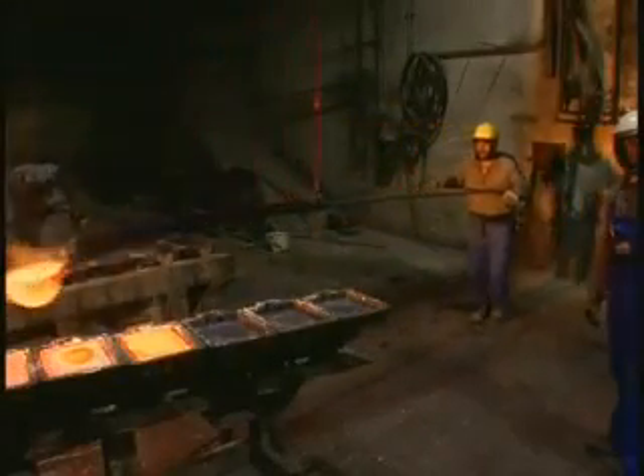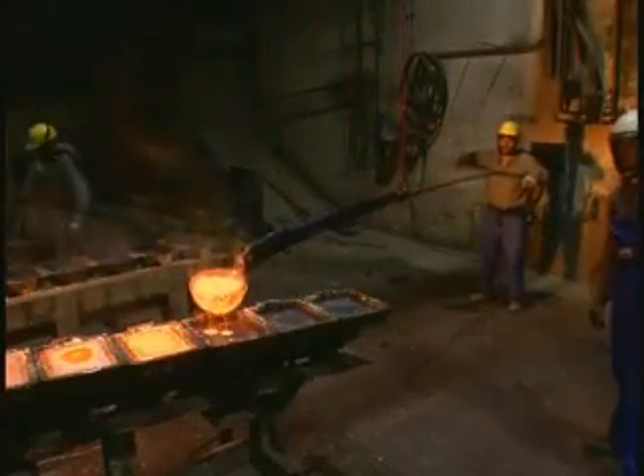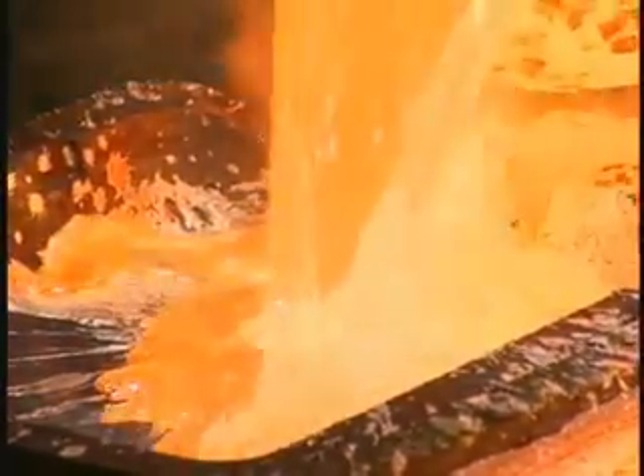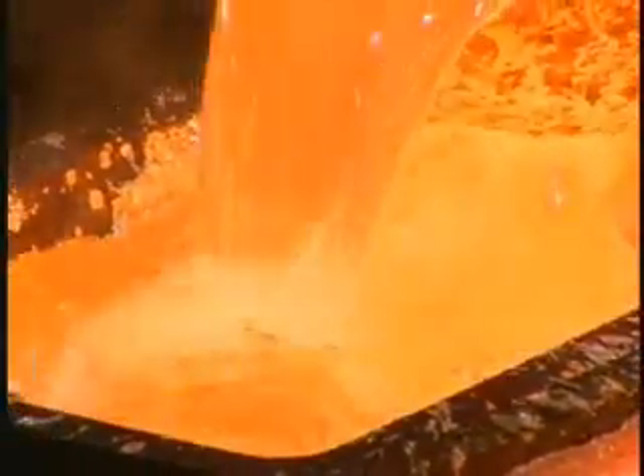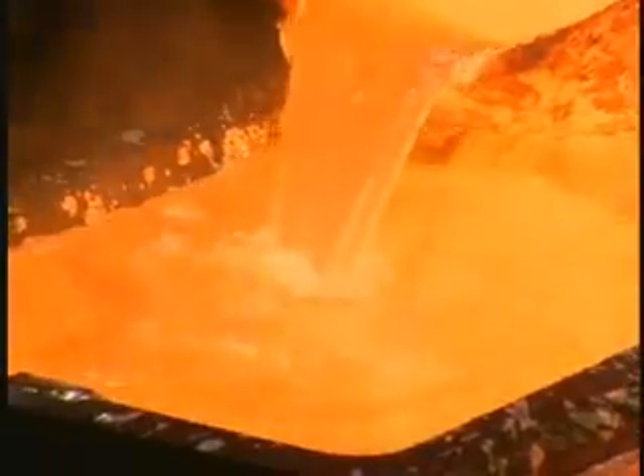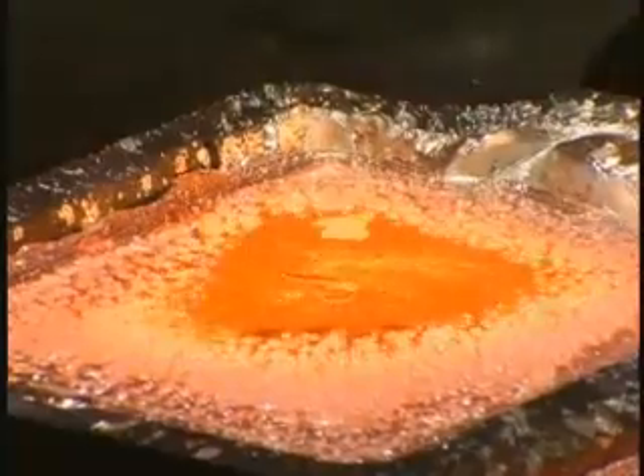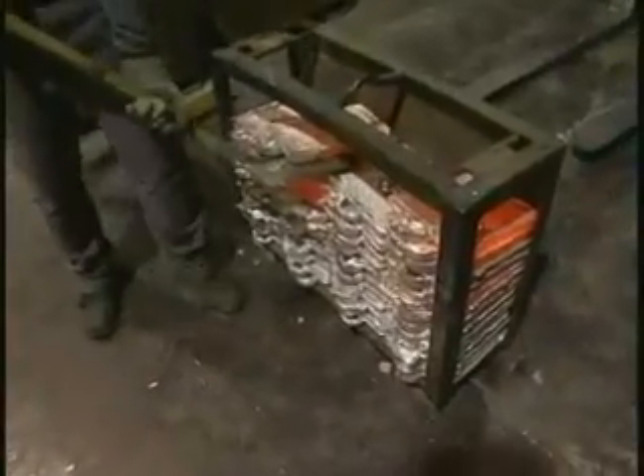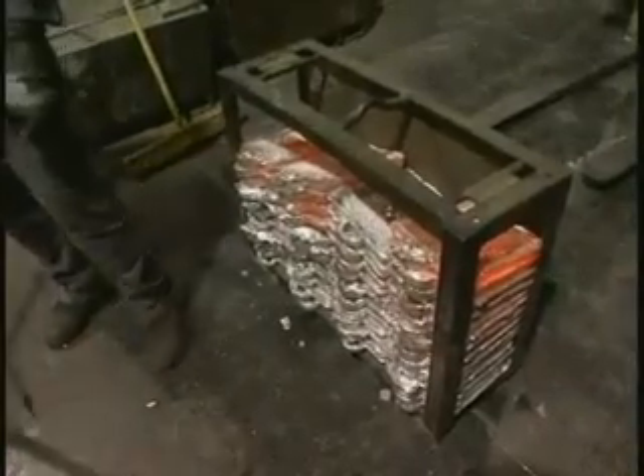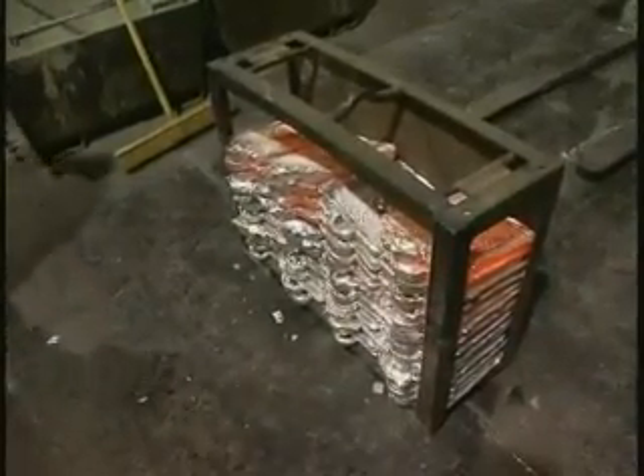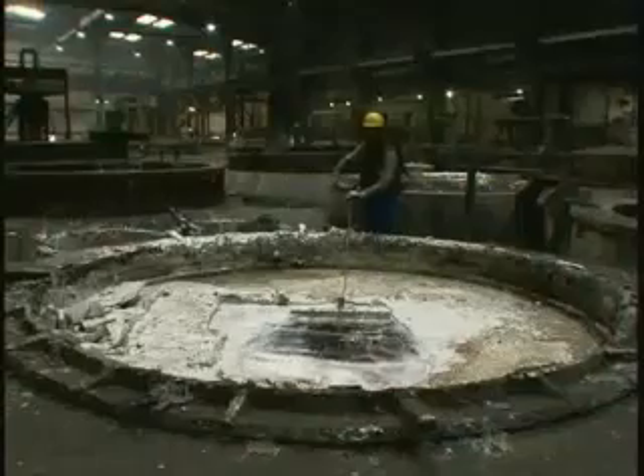In the lead smelter, every year up to 300 tons of silver are produced, for example. In a special cupellation furnace, the silver is freed from the residual lead and cast into handy 14-kilo bars. This is auriferous silver, which contains about 1 per mil gold and 0.1 per mil platinum metals. The dross is reprocessed. The byproducts thus obtained are utilized. This ensures that wastage is minimal.